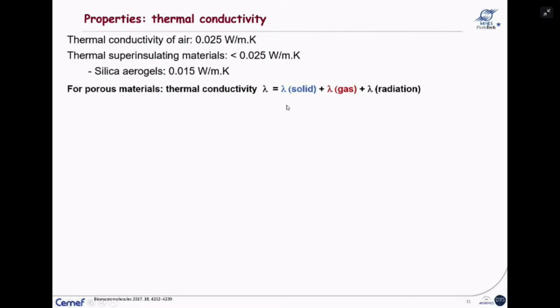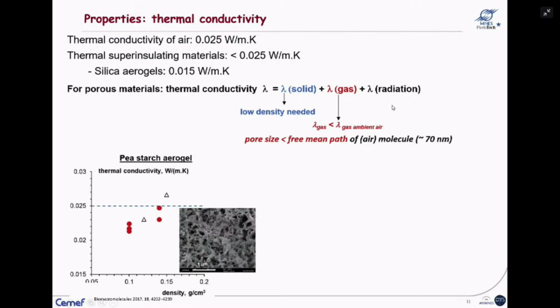So in total, the thermal conductivity is the sum of the conduction of the solid, of the skeleton. So if you want to decrease thermal conductivity, you have to decrease the density. And then also the conductivity of the gas. And there is a Knudsen effect, which is saying that if the pore size is lower than the mean free path of the molecule, okay, here air molecule, then the conductivity of this gas in the confined pore will be lower than the conductivity of the gas of the ambient air. And then radiation conduction is low in this case.